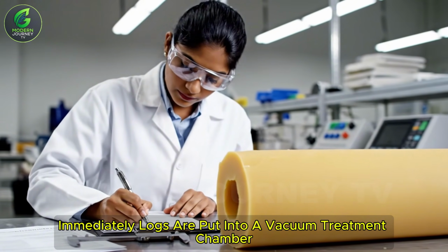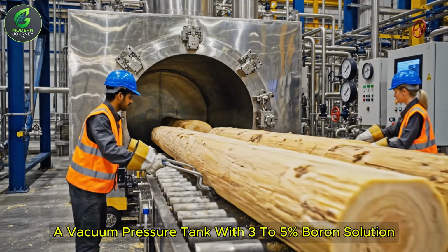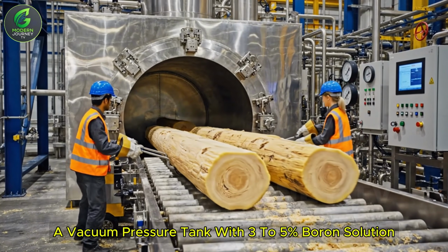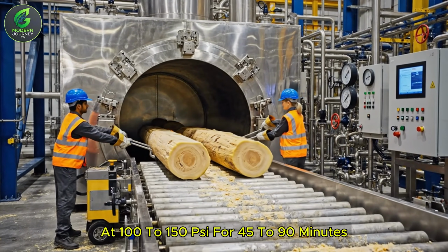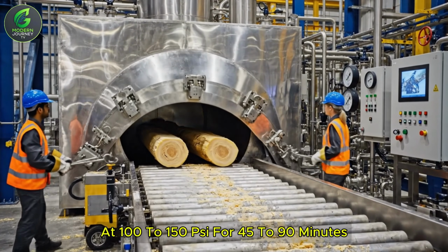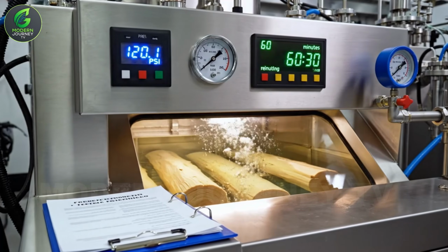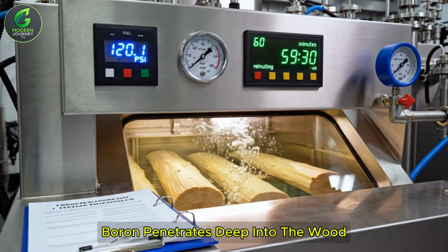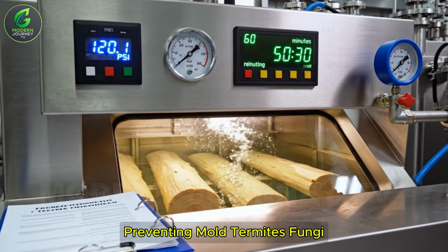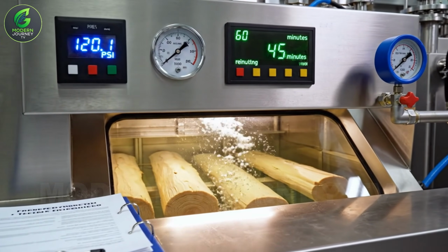Immediately, logs are put into a vacuum treatment chamber, a vacuum pressure tank with 3 to 5% boron solution at 100 to 150 psi for 45 to 90 minutes. Boron penetrates deep into the wood, preventing mold, termites, and fungi. After treatment, wood is safe and ready for sawing.